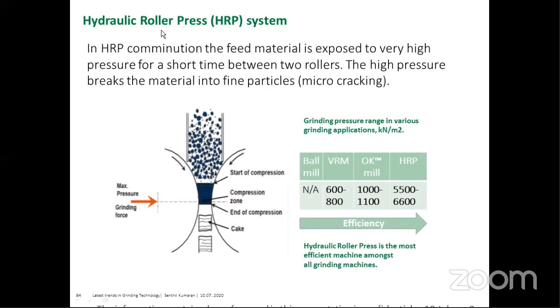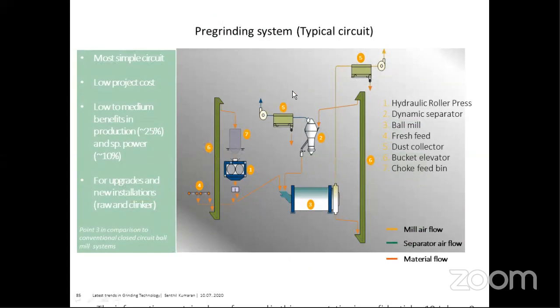In these hydraulic roller press systems, hydraulic force is applied between the rollers and compression starts, and it breaks the material into fine particles through micro cracking. It forms micro cracks and reduces the size. The typical specific grinding force for a VRM is 600 to 800. For OK mill it is 1000 to 1100, and for the HRP, the hydraulic roller press, it is 5500 to 6600. So these are different circuits.